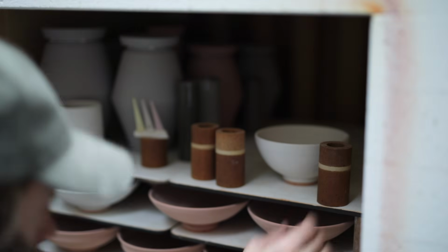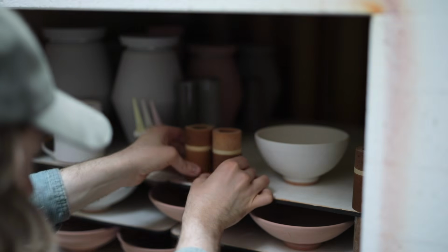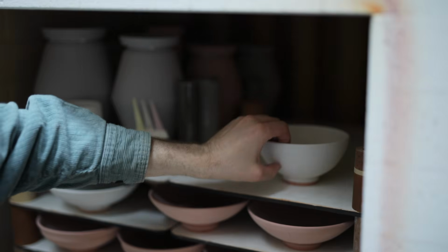The more dense the pack is, the easier it'll be to reduction fire, as there's simply less space for air, oxygen, to exist in. Reduction firing itself is a process where the kiln is placed into such a state where there's too little oxygen for the burning gas to ignite properly. This places the kiln into a reduced atmosphere, and it's this that creates a certain range of colours and textures, and these can be incredibly difficult to replicate in an electric kiln.